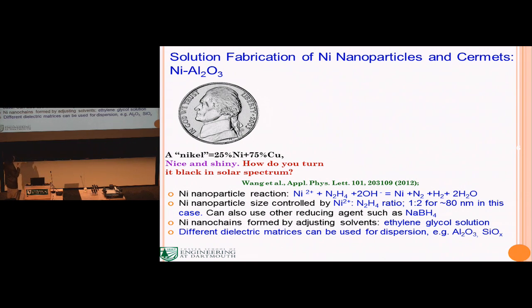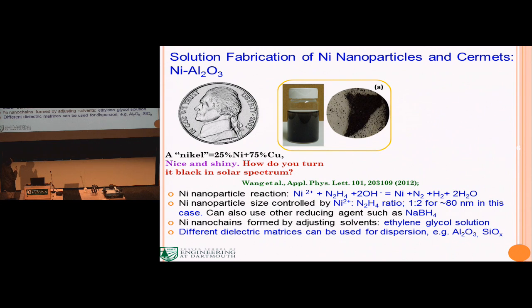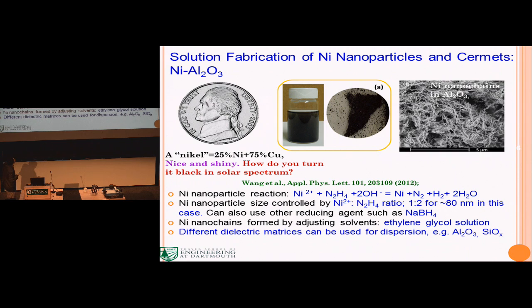So how do you transform this shiny stuff to black stuff that absorbs sunlight? You can use nanoparticles to help with the fabrication. You can synthesize the nanoparticles using chemistry. This is basically what you get. This is the solution. This is the powder. It looks pretty black. And if you look at the nanostructure here, after you mix this with a precursor and coat it on the substrate, you can see this kind of nanoparticle, nanochain structure.